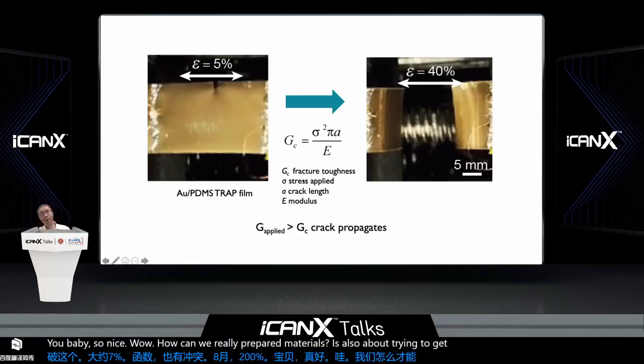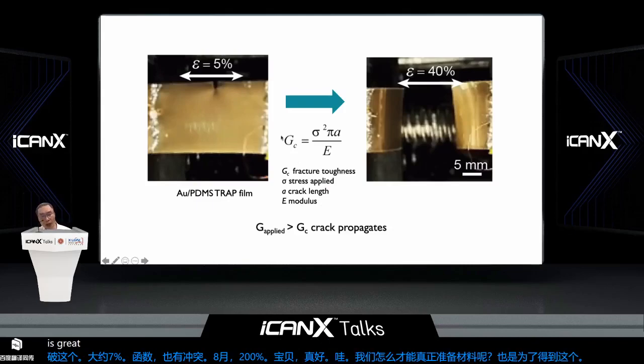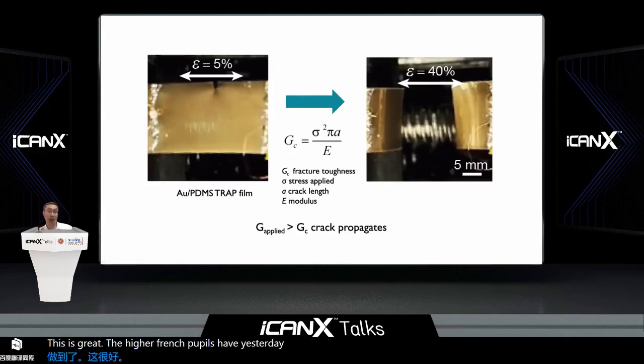And this is something we know already. This is related to fracture toughness. The higher the fracture toughness, the less headache you have about this kind of crack migration issue. And this fracture toughness is related to the applied strength, crack length, the modulus, and so on.